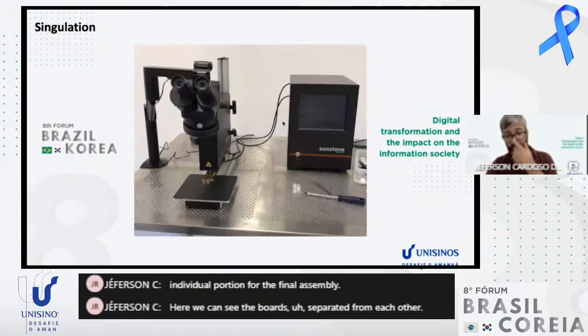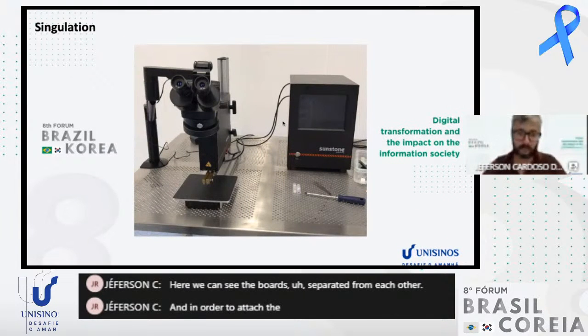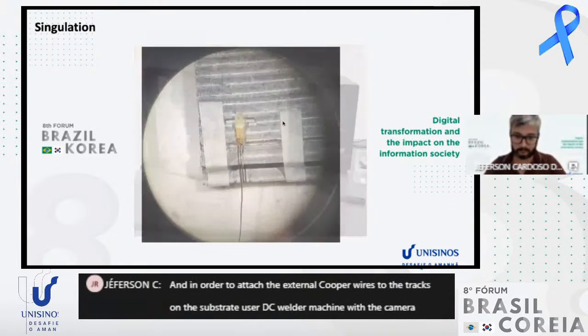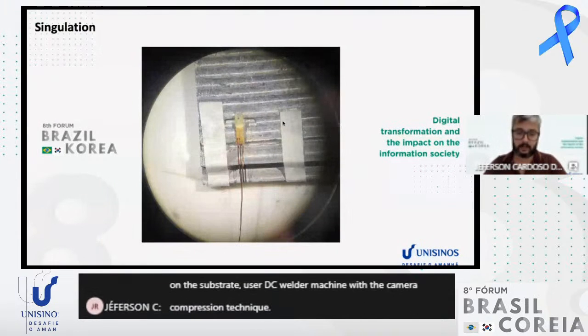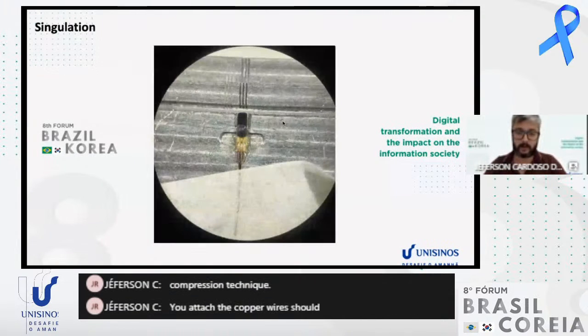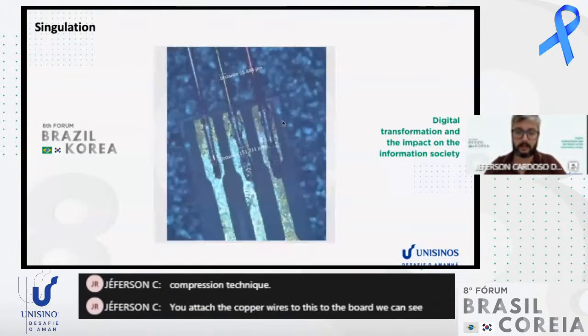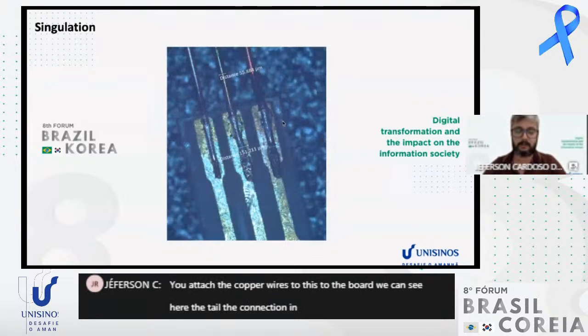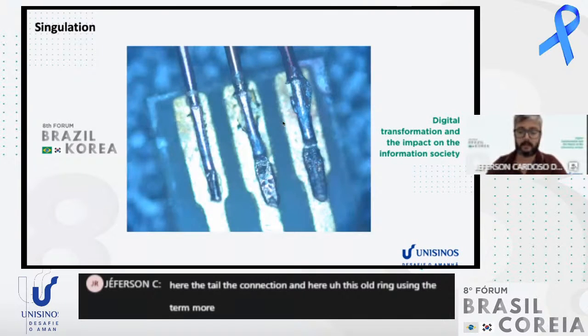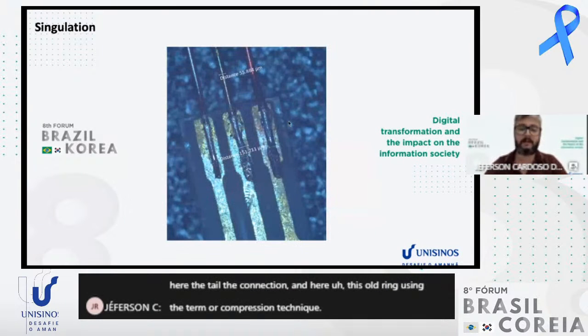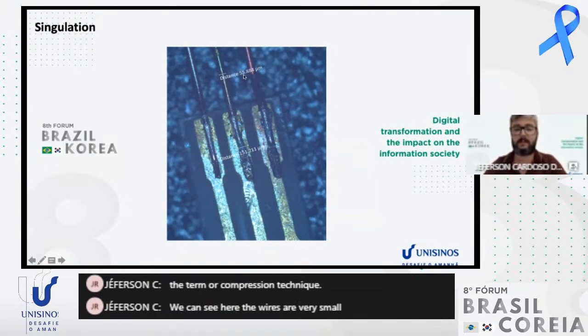And in order to attach the external copper wires to the tracks on the substrate, we used the C-welder machine with the thermocompression technique to attach the copper wires to the board. We can see here in detail the connection. And here, the soldering using the thermocompression technique. We can see here the wires are very small. The diameter is 50 microns.